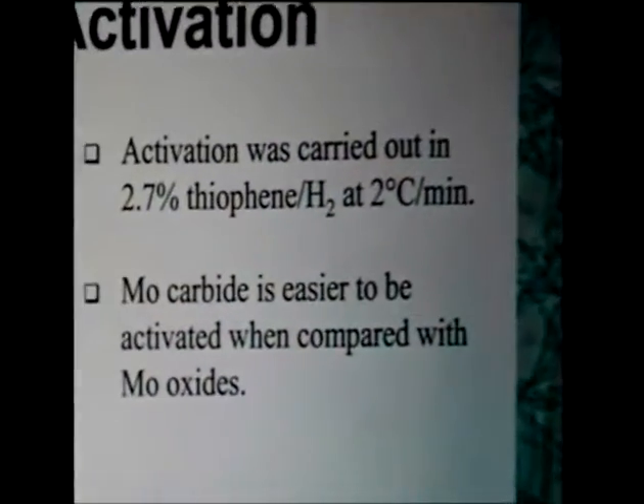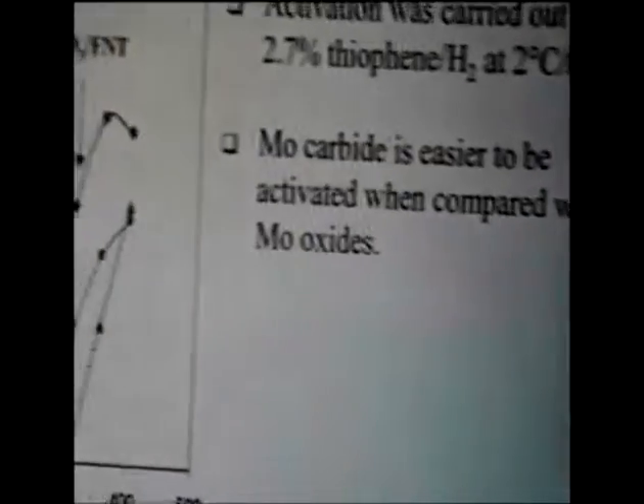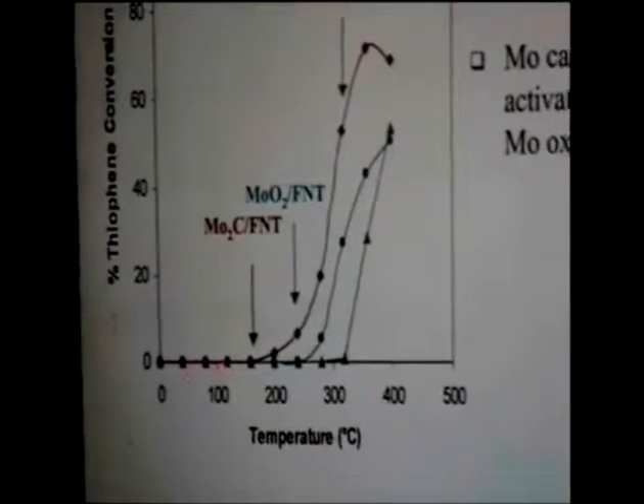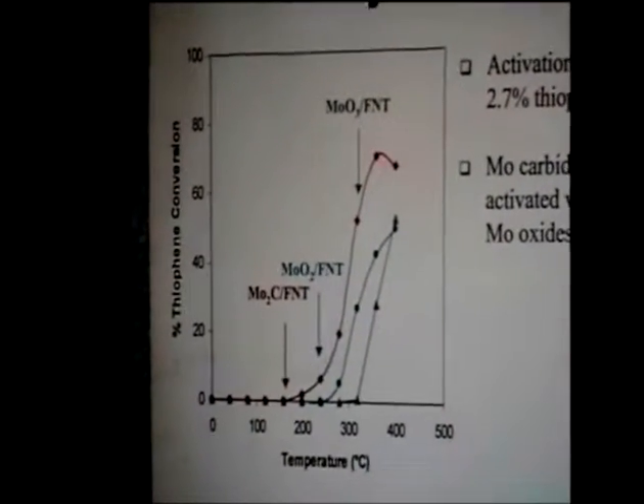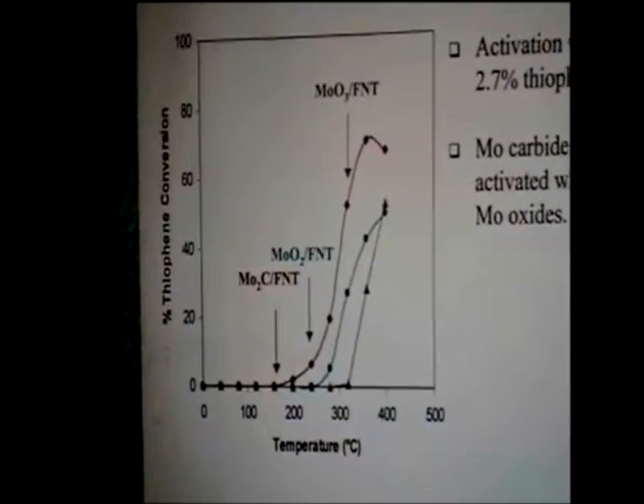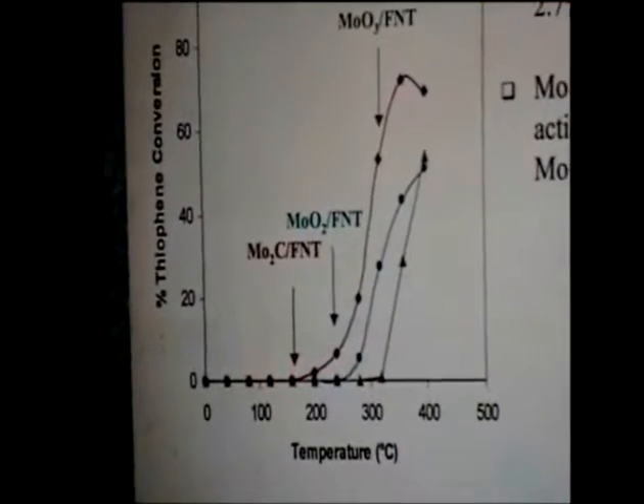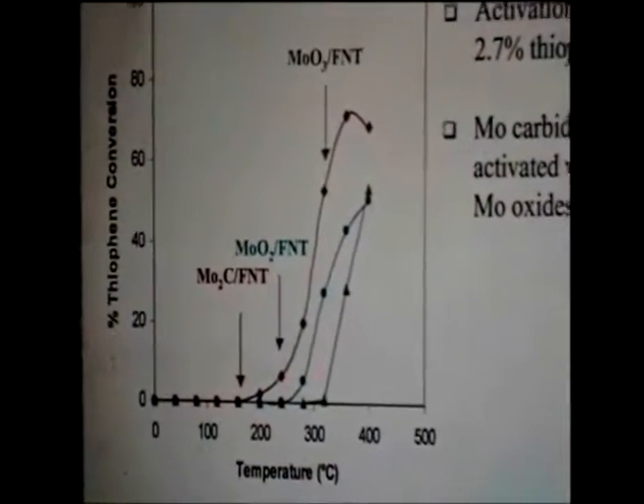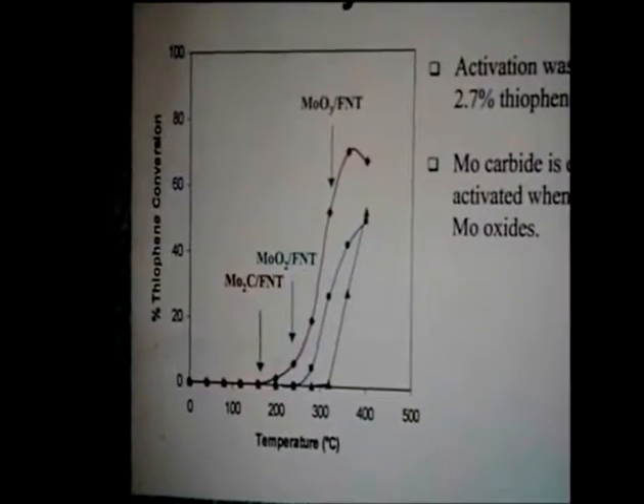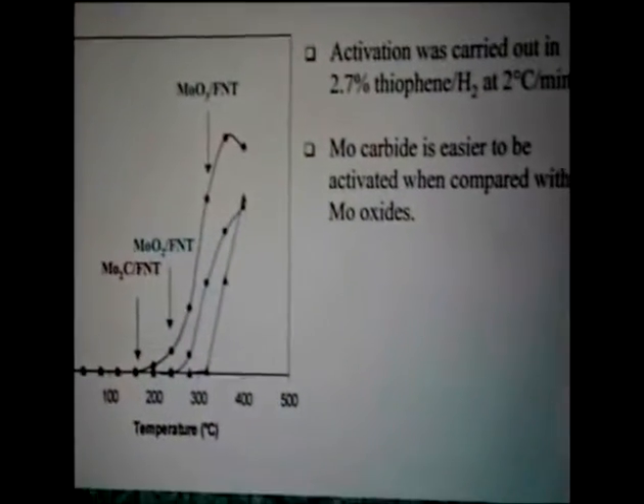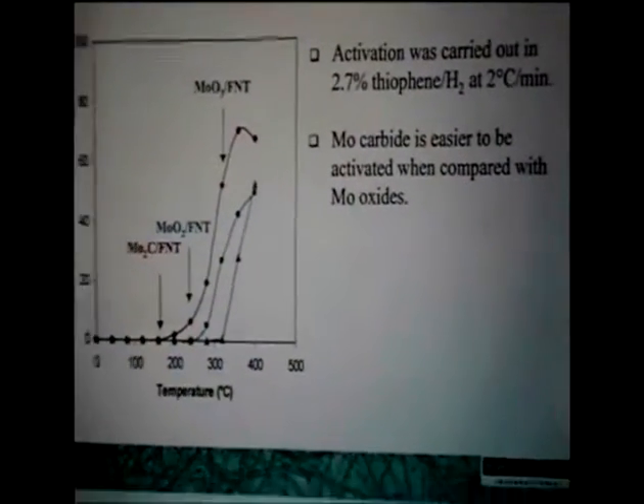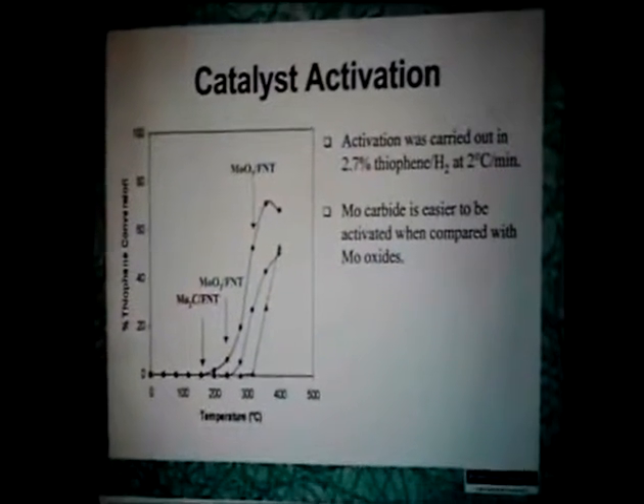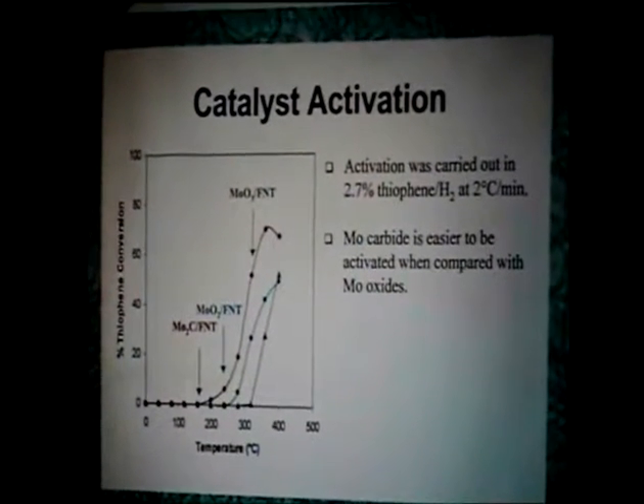So the catalyst activation, we've tried that with thiophene itself. What happens with the conversion as a function of temperature? Here we start with the carbide. Then you can see the activity comes up pretty soon. The oxide, the dioxide takes longer, and the trioxide even longer. It's no question that the carbide is easier to be activated when compared with the molybdenum oxide.